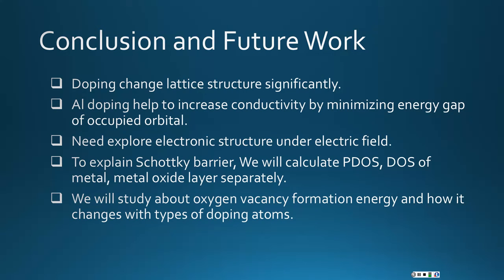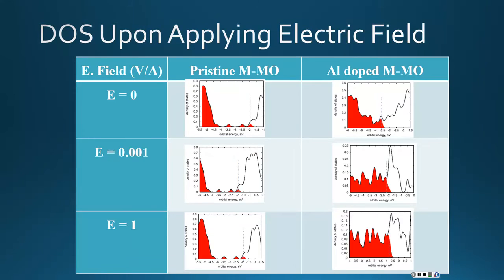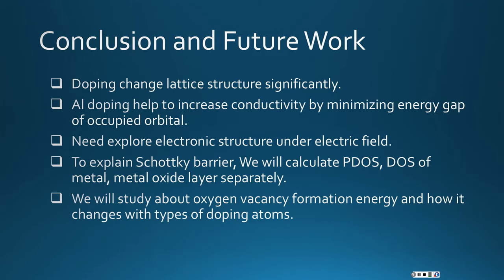So from this DOS calculation, I can say that because of doping, under the electric field, the change in occupation number is huge. So doping can change the lattice significantly, but the most important result is that doping helps to increase the conductivity by minimizing the energy gap and increasing the occupation number in the higher excited state. But I didn't do much work, so there is some future work too. I need to do the PDOS and DOS.